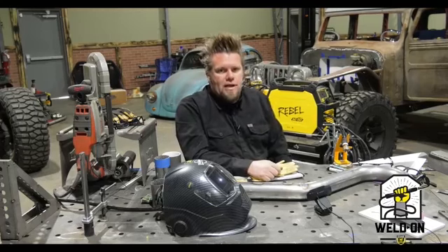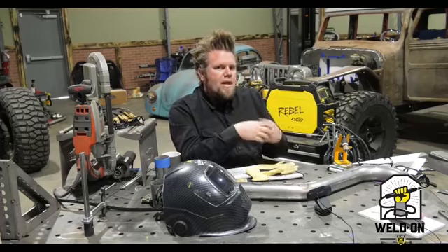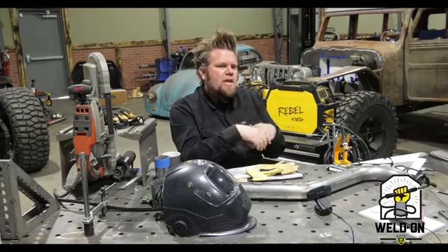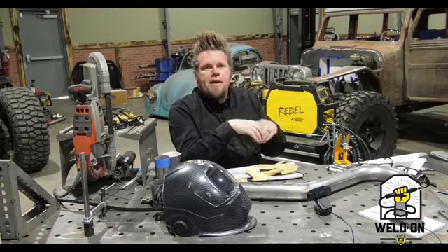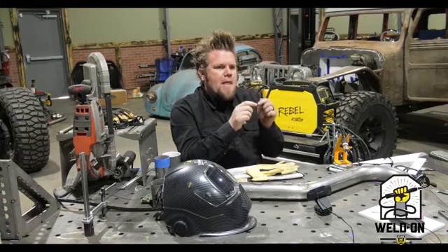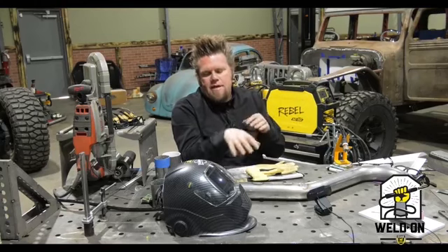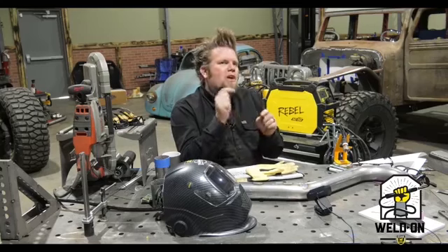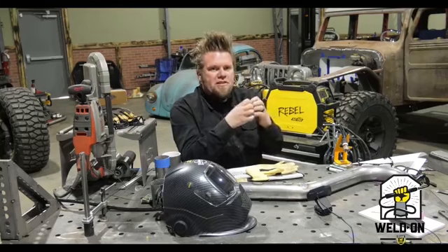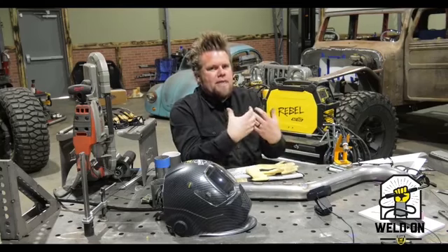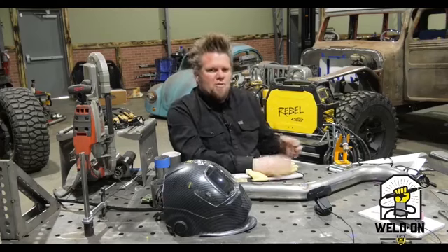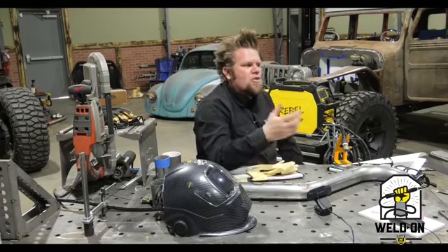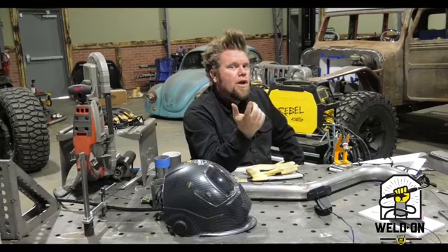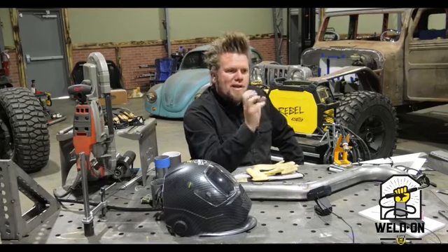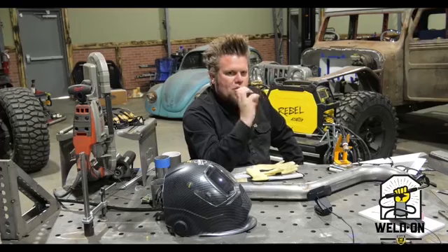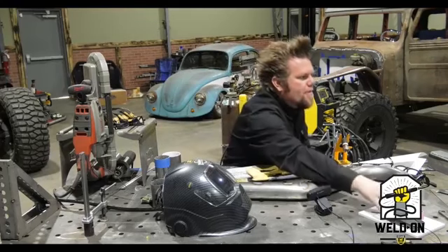Yes, absolutely it is. The problem that people run into a lot of the time when they're adding that filler is they missize that filler because they'll just get a large filler and they end up putting so much heat into the exhaust that they end up boiling the chromium out, because they're trying to weld both pieces of stainless and the filler at the same time. So that's why you'll see most people just stick with a fusion weld when they can. Fusion weld is really good when dealing with headers because it's such a small area that you're working with as well. So there we go.